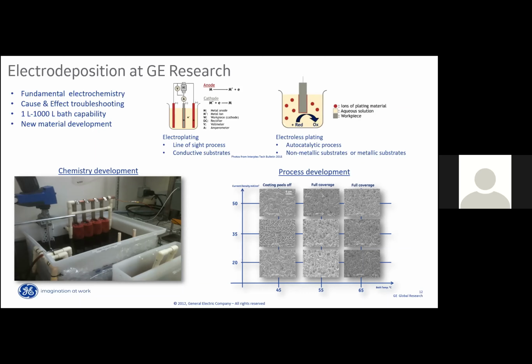We do this routinely where we're given pieces of plastic that are additively manufactured to make them with a smoother texture, basically a cosmetic improvement, right? So we would initially make them conductive by doing electroless plating on this. And all of these processes have been commercially available, industrialized for several years. So one of the best examples of electroless plating is doing electroless nickel in printed circuit boards to avoid oxidation.